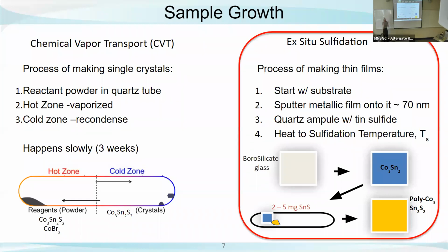So we start with a substrate and then we sputter a metallic film on it. Usually it's cobalt-3 tin 2. And then we throw that little film into a quartz ampule with a little bit of tin sulfide. And then we heat it to a sulfidation temperature.